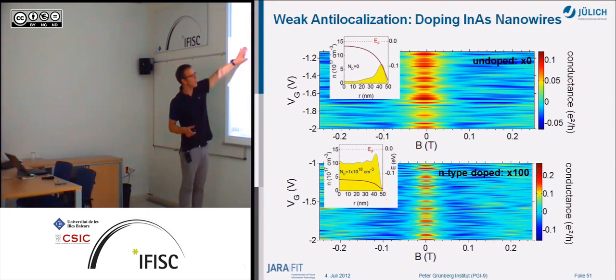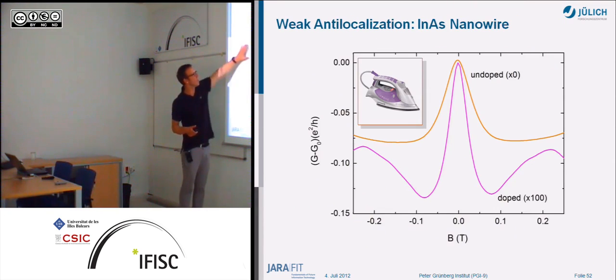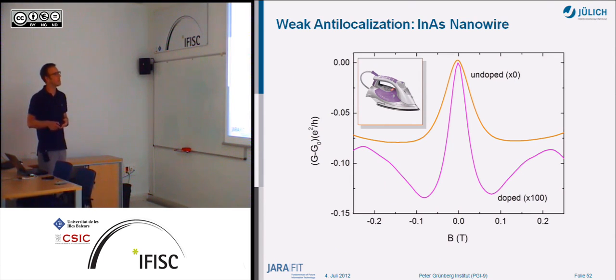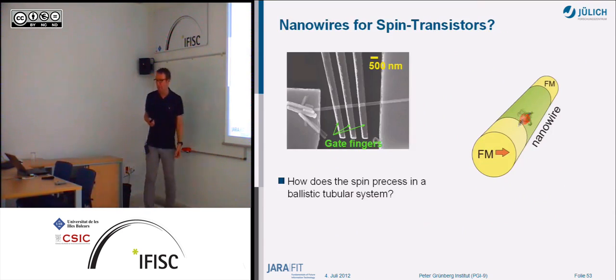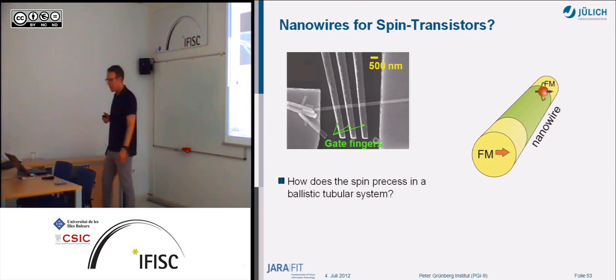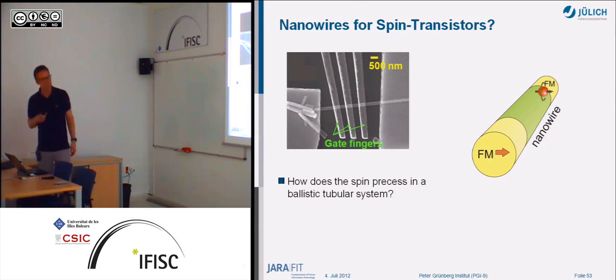So these are measurements from the last week. This is a doped nanowire, an undoped nanowire, and you see some differences here in the weak anti-localization. Just to show you how far we are, we still have to analyze this, but we definitely see that for the doped nanowires we get a sharper peak compared to the undoped nanowires. That's something we try to figure out, what's going on in these nanowires if we change the potential profile by doping here.